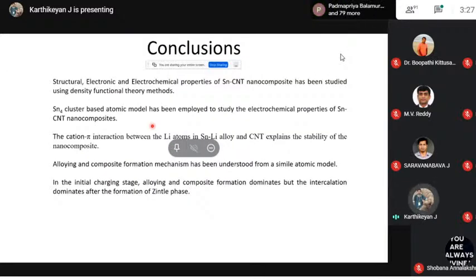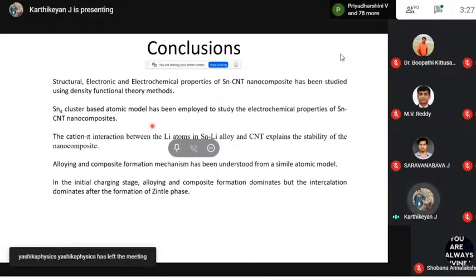So we have studied the structural, electronic and electrochemical properties of these nanocomposites, and the main stability of these composites comes from the cation-pi interaction between the lithium atoms in tin-lithium alloys and CNTs, and the volume expansion is really minimized when you use multi-wall CNTs. That is also demonstrated in this work.